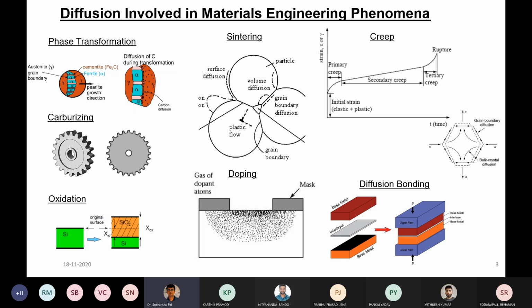And what you want in the carburizing process is that the surface will have more carbon inside the low carbon steel, so that at the surface the steel will be hardened. If the carbon percentage in the steel is increased, then the hardness will be enhanced, as well as the wear resistance of that particular position of steel where the carbon percentage is high. And there are different methods: pack carburization, gas carburization, liquid carburization, vacuum carburization.